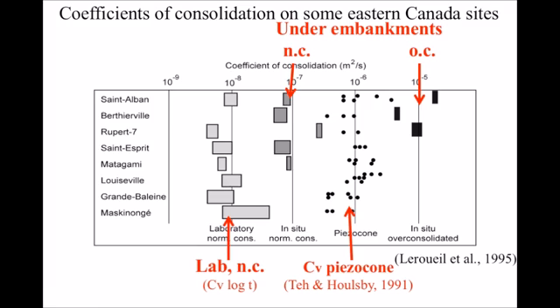Now, if we consider the CV values obtained in oedometer tests and analyzed with the log-t method, the CV underestimates the real value in situ, typically for our clays by a factor of 10, which is significant.